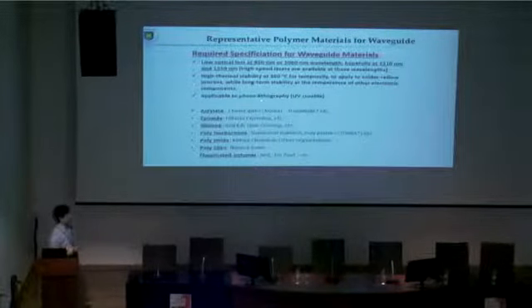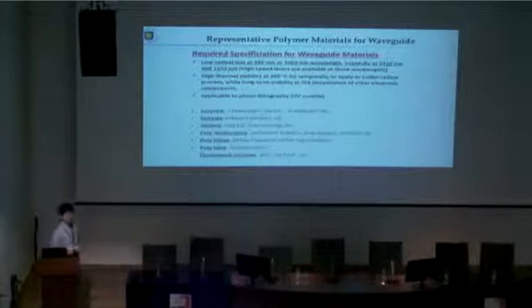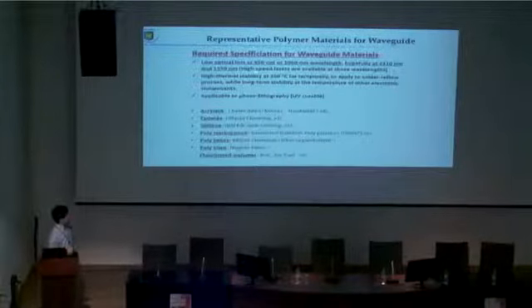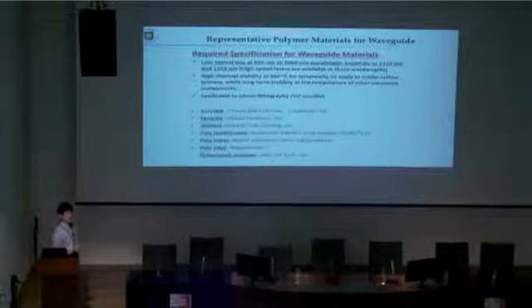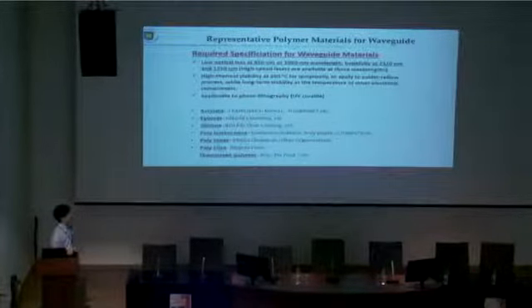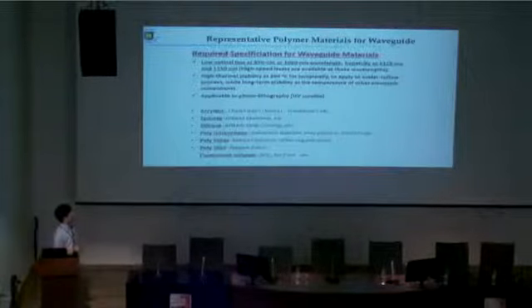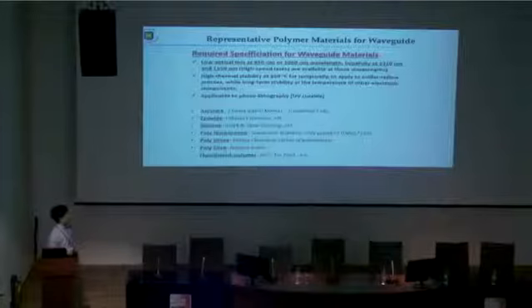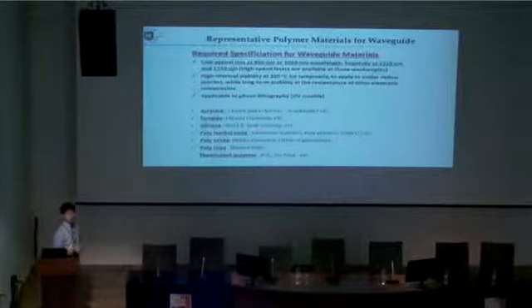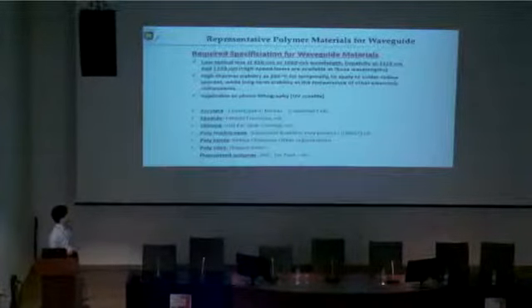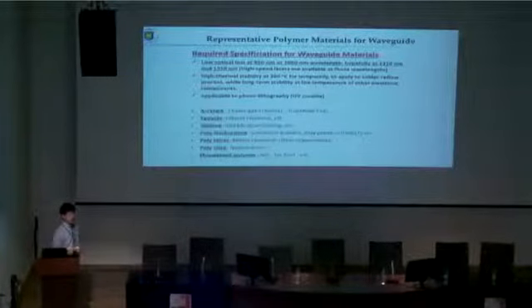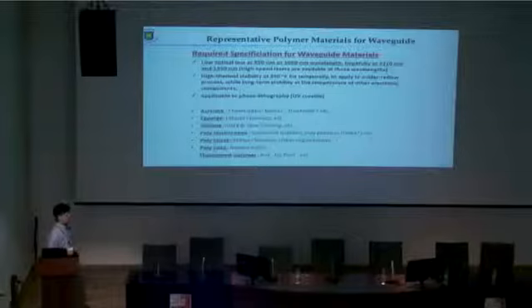And in general, the required specifications of polymer materials are, as you can imagine, low optical loss, hopefully at 850 nanometer or 1060 or longer, like 1310 or 1550 nanometer. In addition to these optical characteristics, for optical PCB applications, high thermal stability at 260 degrees C is preferable in order to apply to the solder reflow process. While long-term stability at the temperature of other electronic components is also required, like 85 degrees C, 85% RH. And application to photolithography or UV cure is another specification for polymer material.